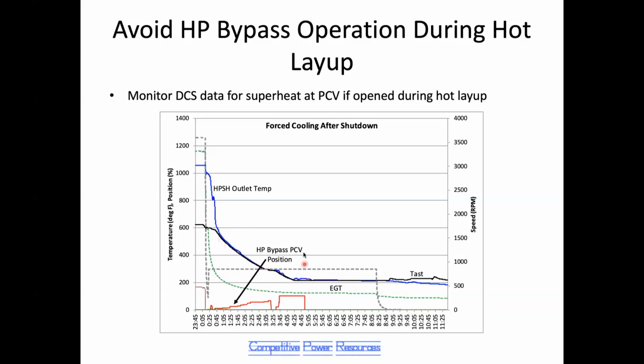Now, I don't have the data here, but I will tell you this behavior is somewhat unit specific. Some units have enough residual heat in the gas path that this steam temperature doesn't come down so rapidly, and it'll take longer for it to reach saturation. Other units, if you don't immediately start this depressurization, but you wait a couple of hours and then you start it out here, the saturation temperature has decayed to the point that you may not reach saturation during this event. But you have to look at this kind of data in order to determine how your unit's doing it.